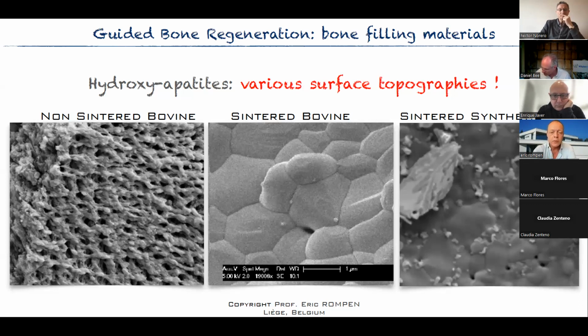In the middle part, we have a sintered bovine hydroxyapatite. Sintered means heated above 1000 degrees. And when you heat the bovine hydroxyapatite above 1000 degrees, then we really melt it, and it becomes very soft, very smooth, and then you kill the osteoconductivity. And it's the same for synthetic hydroxyapatites. Most synthetic hydroxyapatites are also sintered and very smooth.